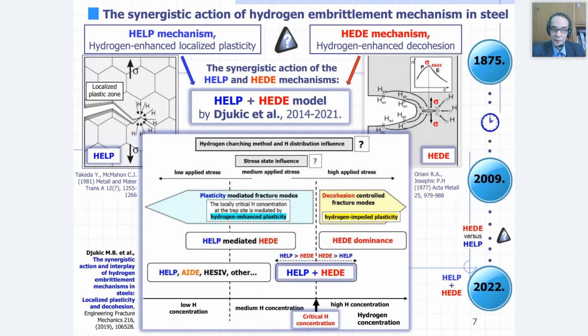A group of researchers from the University of Belgrade in 2014 and 15 proposed the now widely accepted and highly cited HELP plus HEDE model about the synergistic action of both HELP and HEDE mechanisms in materials. On the down middle part you can see the diagram which summarizes the HELP plus HEDE model. This diagram is published in our critical review paper published in 2019 about the HELP plus HEDE model. As you can see, what is important is hydrogen concentration. At critical hydrogen concentration, we have a change of mechanism from HELP plasticity mediated dominance to HEDE decohesion.